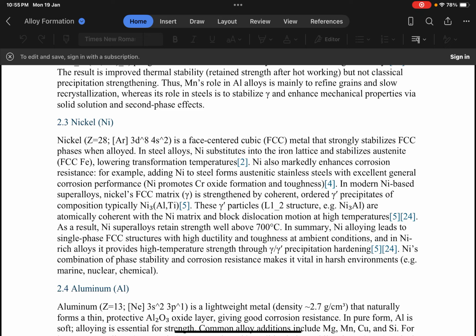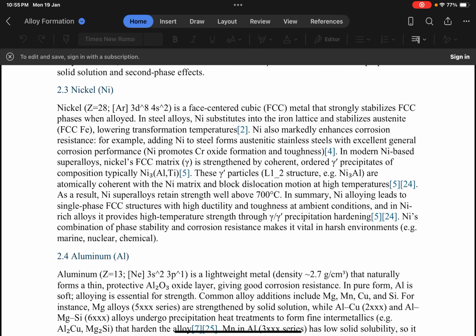Nickel has a face-centered cubic structure and strongly stabilizes face-centered cubic phases in alloys. In steels, nickel improves toughness and corrosion resistance, especially at low temperatures. In nickel-based superalloys, nickel forms the matrix phase known as gamma. Strengthening occurs through the formation of gamma prime precipitates, usually nickel aluminium. These coherent precipitates block dislocation movement even at very high temperature. That is why nickel alloys are used in turbine engines and aerospace applications.